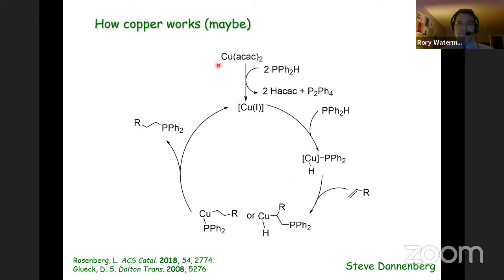So as I was explaining before, copper ACAC in the presence of phosphine protonates off ACAC and forms tetraphenyl diphosphine, which gives us a copper 1 intermediate. There's doubtlessly some more complicating chemistry here because there is something that supports copper. We're not just making copper 1 free floating in solution. Critical to that is some kind of P-H activation event. I sort of loosely draw this in some way, and I only draw it because there is the possibility for a copper hydride versus a copper phosphide insertion process that prompts this reactivity. And in either case still gives us the regioselectivity that we would expect for the product.